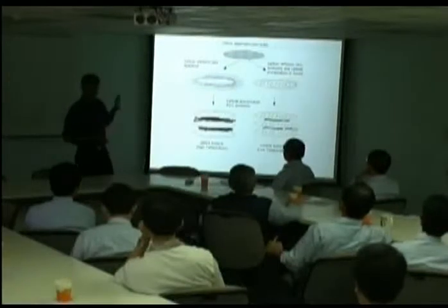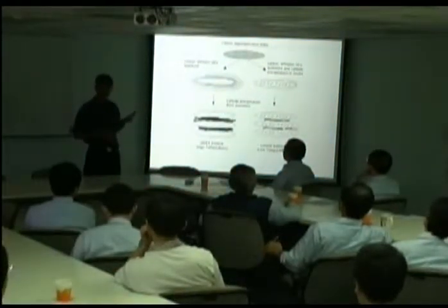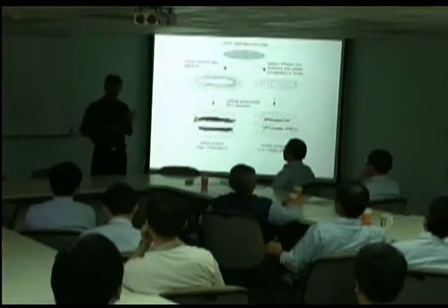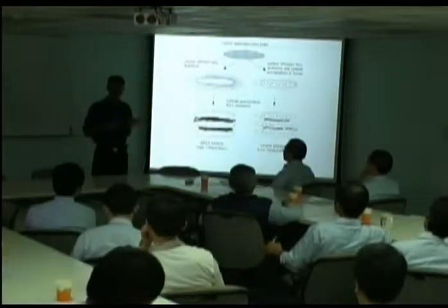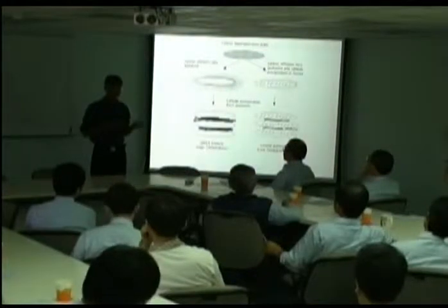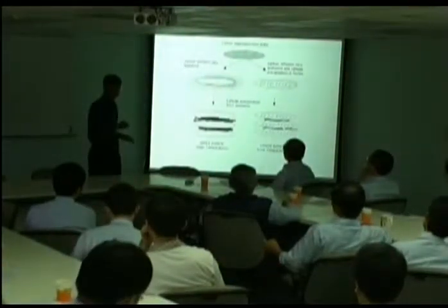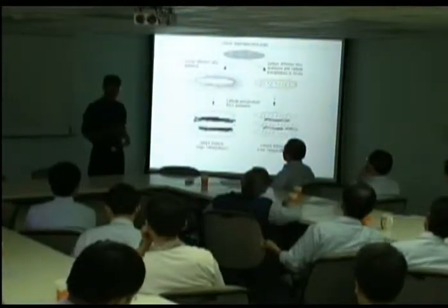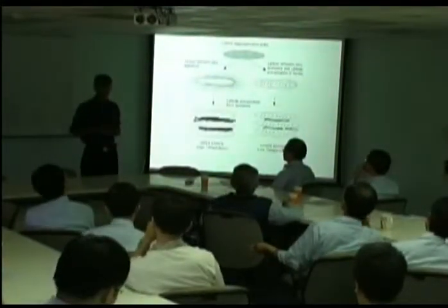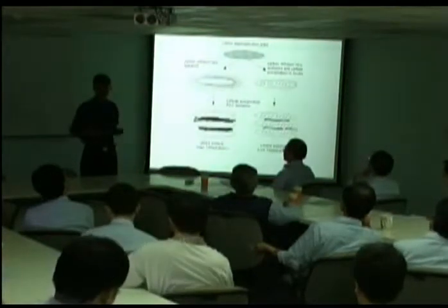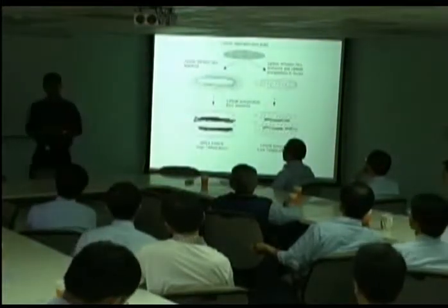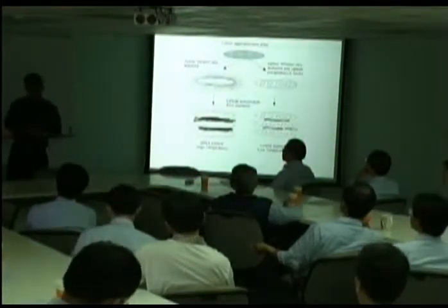Now, we have produced a quantitative model for the transition from upper to lower bainite. And it's a very simple model. It compares the time taken for the carbon to escape from the plate with the time taken for carbon to precipitate inside the plate. If the time for diffusion is smaller than precipitation, then we have upper bainite. If the time for diffusion is greater than precipitation, we get lower bainite. And when we did this model, at first we didn't believe the results,